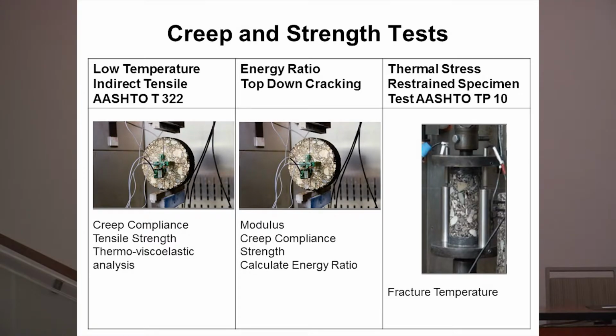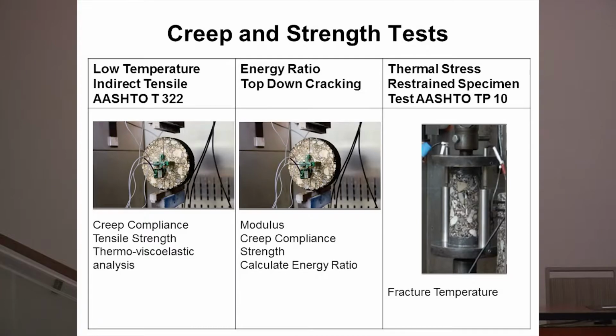In this case, same geometry. Here you measure modulus, compliance of the material and strength, and calculate an energy ratio, which is basically the resistance of the mix to cracking divided by the potential for the pavement to crack. It's a fairly simple calculation that is done. Then there's the thermal stress restrained specimen test. You put a specimen between a couple of plates, drop the temperature, and wait for it to crack. Since it doesn't move, the thermal contraction is going to build up stresses, and the parameter you get out of it is a fracture temperature.